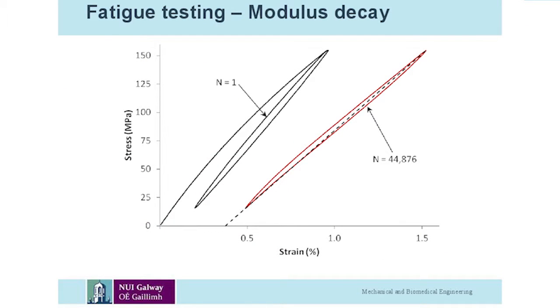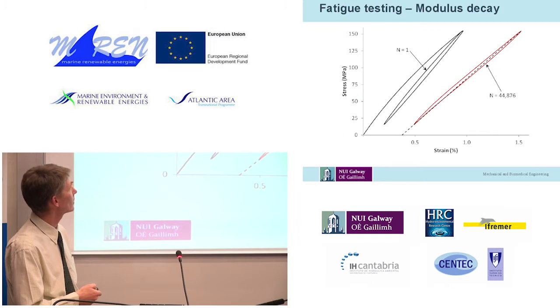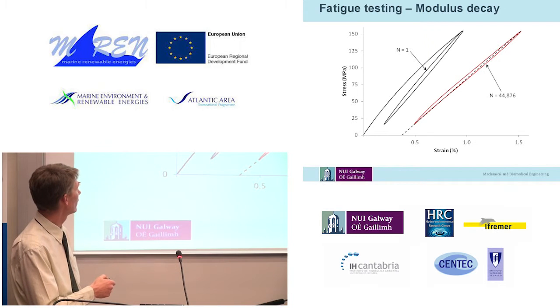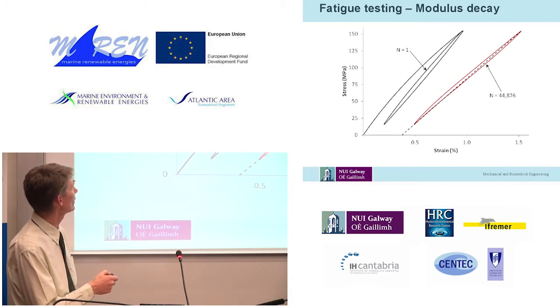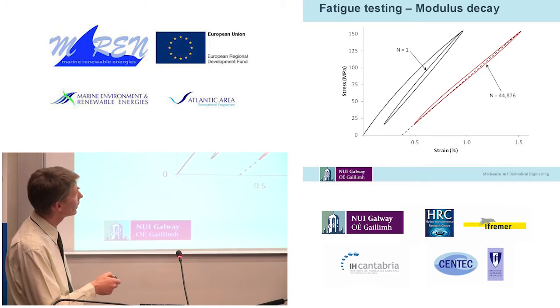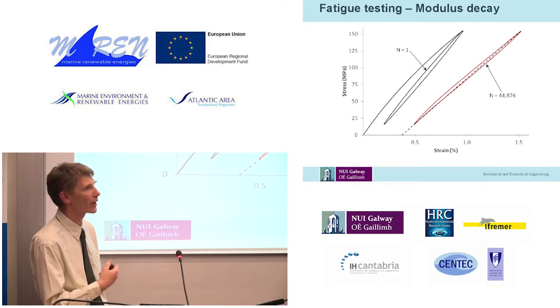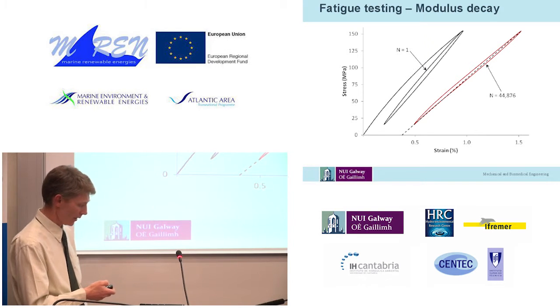So the other thing that we monitored during the fatigue testing was the modulus or stiffness decay of the material, and in particular what we monitored was what we call fatigue modulus. This is the stress-strain response of the material, and that's the very first one, and then there's the first loop there as the material goes around, and then you can see that as the fatigue cycles go on, it leans over a little bit and we get a lower stiffness.